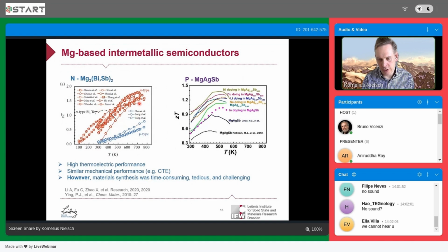You can see here peak ZT values close to 2 at, for example, 400 centigrade, 700 Kelvin. And you have an average ZT above 1, starting from room temperature to, for example, 400 centigrade. For the P-type material, the magnesium silver antimonide is very promising. This can be operated up to roughly 300 degrees. A few slides later, I will mention why there is some limitation for this material in terms of temperature. But in principle, you can also see here very promising ZT values, with an average ZT above 1 over the whole regime. This is very promising on one hand for thermoelectric cooling, but on the other hand also for waste heat recovery.